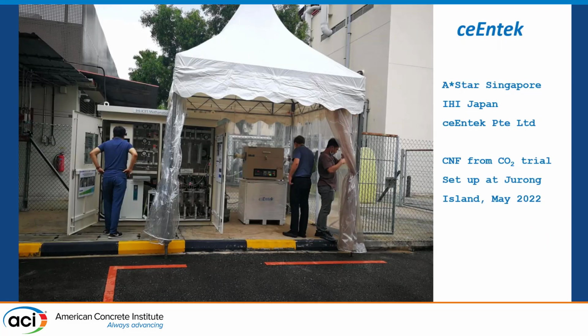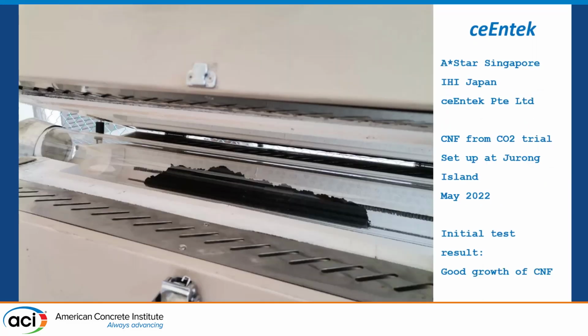One of the great things about this is we've proven that you can use a waste stream, CO2, to make your carbon nanofibers. So once you capture CO2, you can use it to produce these carbon nanofibers, which is a huge advantage for sustainability. In a demonstration product that we've done, we were able to grow very good quality fibers, and we had good growth of those fibers. And this is the technology, this is the innovation that we're really excited about, because it does open that door to using waste streams of CO2.